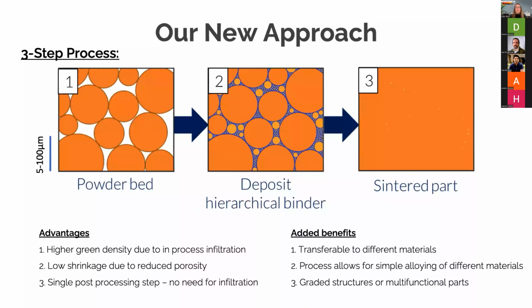So because of these types of binders, we're simultaneously infiltrating the powder bed and we're binding, we can remove some of those process steps. So remember the previous slide where we saw that 4 or 5 step process, we're now reducing that to a 3-step process. That means reducing manufacturing time, but also we find that we can often lower the processing temperature at which we need to heat treat, as well as shorten that time required for sintering.